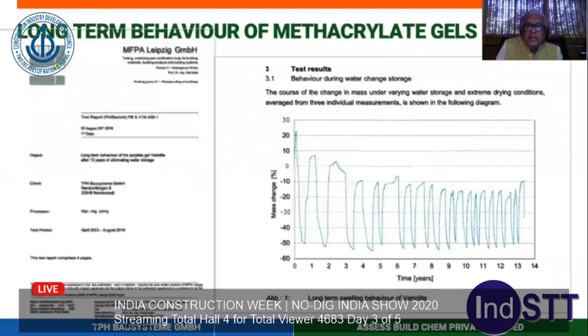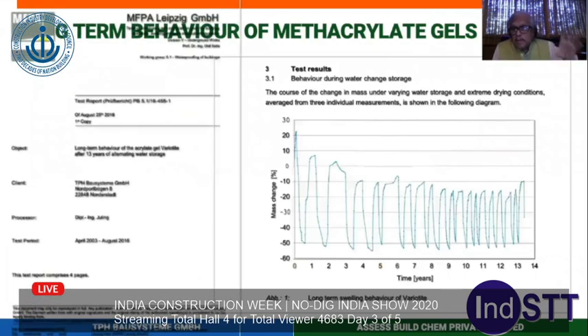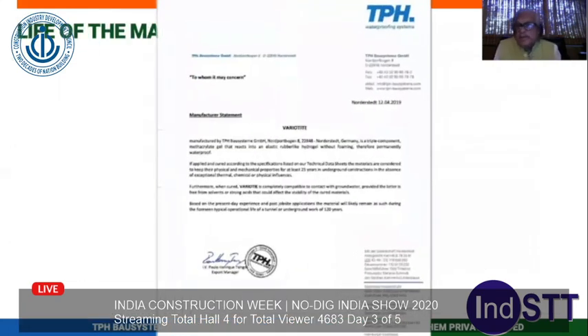And the durability testing: these gels are liable to expand and contract when they are inside the mud, or in connection with water. Now this has been tested up to 14 years in the field. When there is less water, it shrinks. When there is more water, it expands. You can see the cycles over a period of 14 years, and this can be extrapolated. The engineering estimation of durability of this gel is 120 years, as compared to your